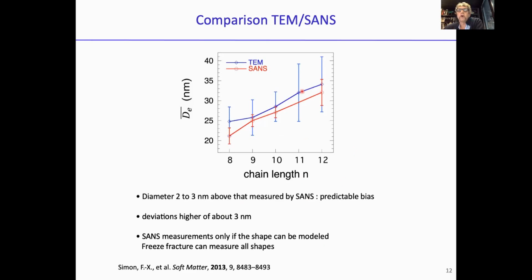For instance, for 12 carbon, we don't see any nanotubes, and it's impossible to make a model. So we don't have a measurement for this. So it shows that freeze fracture electron microscopy is a very practical and very direct method to see the objects and to measure a size, provided you can predict the bias of these pictures.